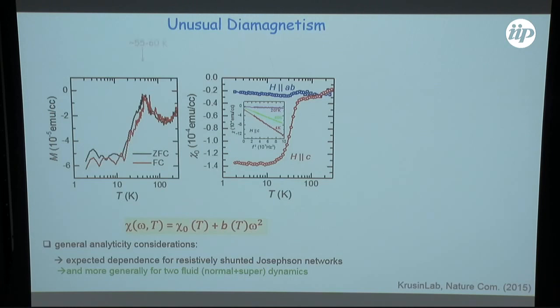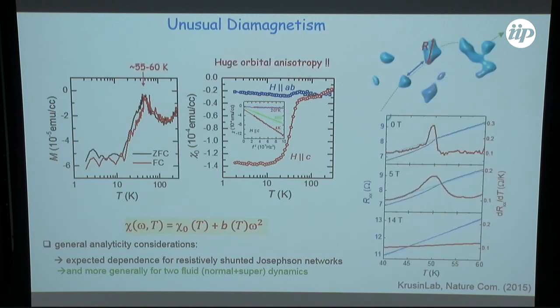So somehow we have a puddle system, and actually we see a very small resistive signature which disappears at high fields in resistivity as well. But this is very hard to track because it's a very tiny blip on the whole landscape.